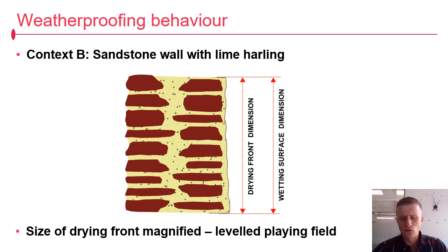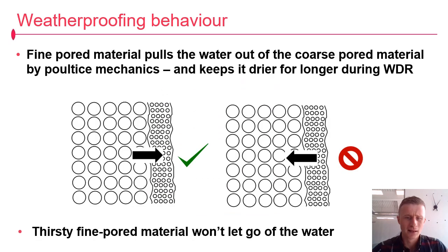So you've now levelled the playing field between the propensity of the wall to get wet and its ability to dry back out, significantly enhancing the drying capability. But there's more going on there, so we'll probe poultice mechanics in a wee minute. Essentially, a fine pored material will soak water out of a coarse pored material into itself. That's like drawing the body of water out of the coarse pores into itself, closer towards the drying front. It also keeps the coarse pored material drier for longer.